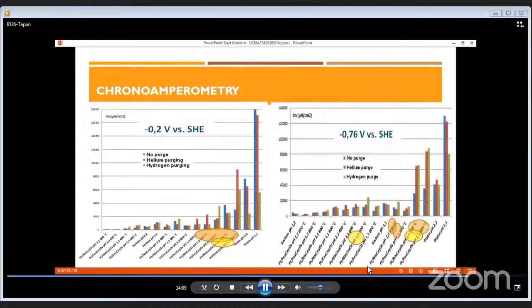And finally, we have performed chronoamperometric experiments at the applied negative potentials determined from cyclic voltammetry, at different pH and potentials and at different reduction temperatures. You can see on the right steady-state curves for different catalysts at different conditions. And this graph shows the order of steady-state curves from chronoamperometric experiments at different conditions. We can say hydrogen purging has a higher effect on steady-state curves at more negative potentials. Then, first the reduction temperature and then the pH have a dominant effect on steady-state curves.